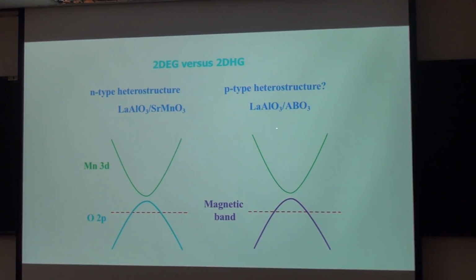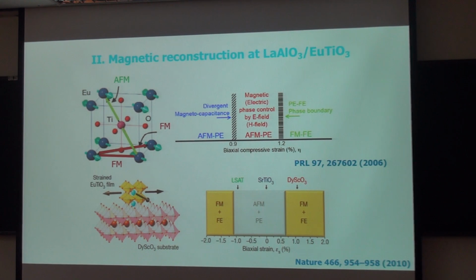So we should change from this so-called charge transfer insulator to the Mott-Hubbard insulator, or change the so-called magnetic valence band in this ABO3 polar-nonpolar material. And we have found a very suitable material, that is europium titanium oxide. In this system, we have realized the charge transfer induced two-dimensional hole gas, which is also spin polarized.